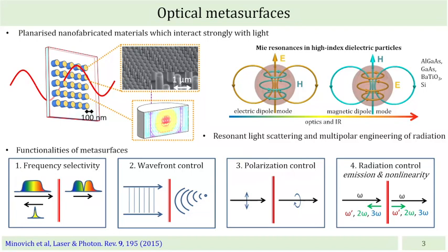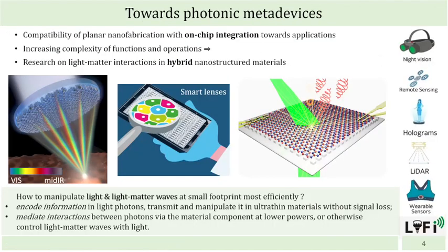Functionalities of metasurfaces are therefore largely based on the physics of resonant light scattering, such as Mie theory, and by designing the lattice arrangements and particle shapes, metasurfaces can perform a range of functionalities for radiation control. Planar fabrication of metasurfaces is compatible and quite similar to chip making.